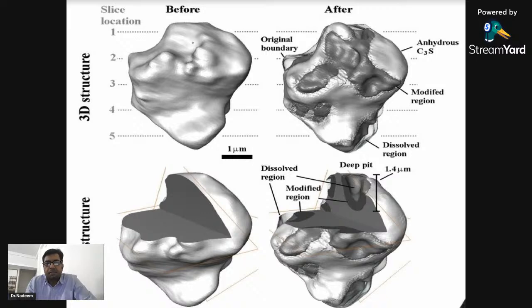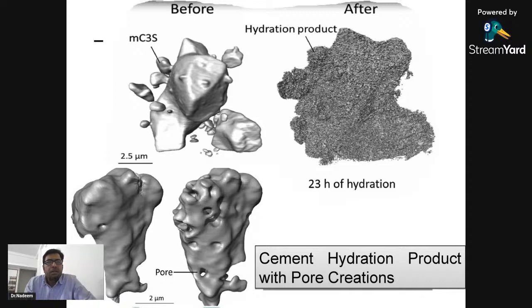We'll see subsequent slides. Once the reaction is happening, each particle is reacting, but a lot of shrinkage is happening, a lot of pore creation is happening in the particles, because of the water we added, only 50 to 60% water gets into a reaction, otherwise it just evaporates, which creates a lot of pores in cement or concrete. So this is how a cement particle, and this much size of a particle, gets reduced into a hydration product after say 24 hours.